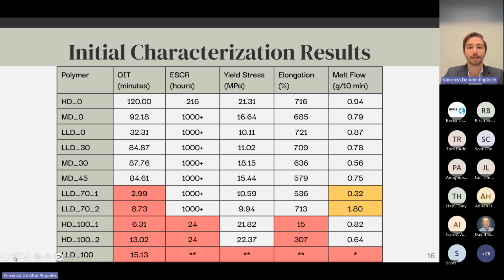Further, it should be noted, all of our initial characterization testing was done on the type A, more strenuous ESCR tabs. And as such, we do believe that the HD samples may have passed if they were subjected to the less strenuous type B, which is what they're expected to be tested against.